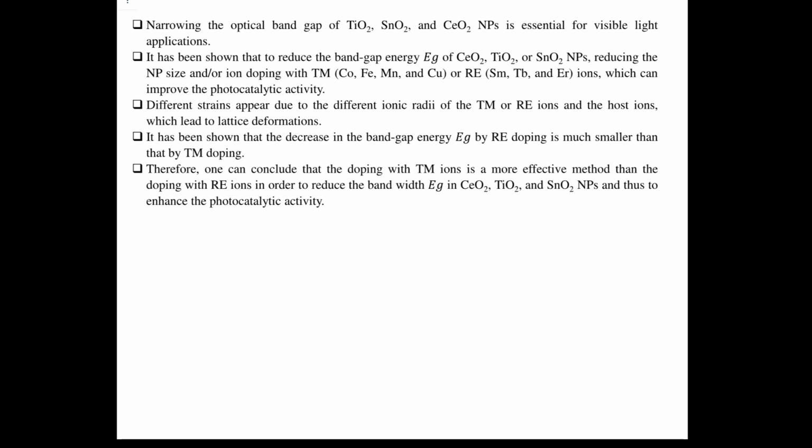One more important effect of these impurities is that they also act as electron traps for the valence band electrons, thereby diminishing the electron-hole pair recombination. Under normal conditions, when you irradiate the materials with some light, the photocatalytic activity is less due to the electron recombination.